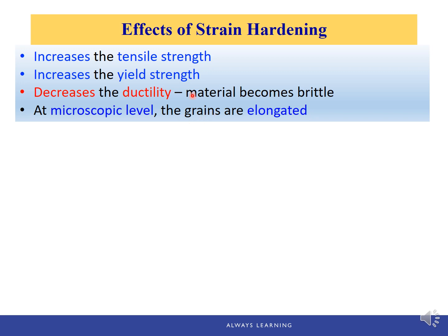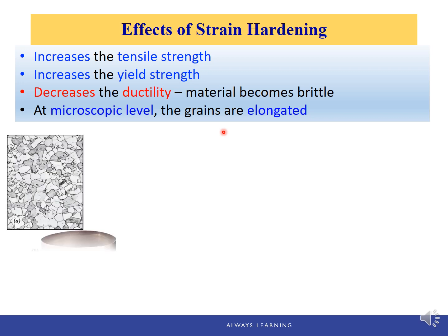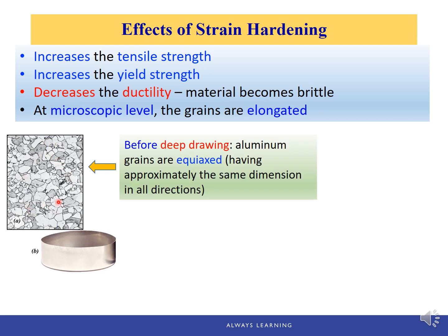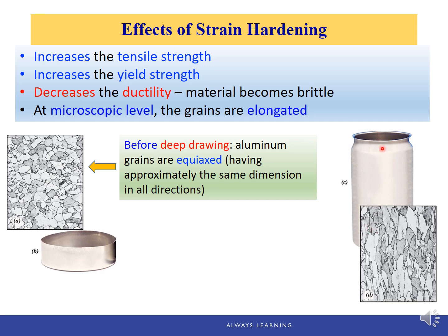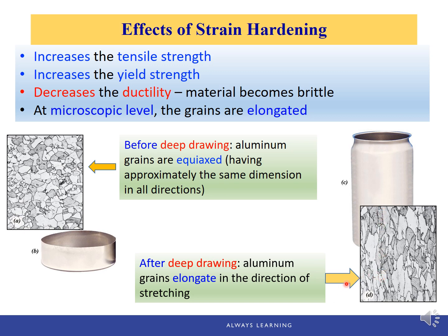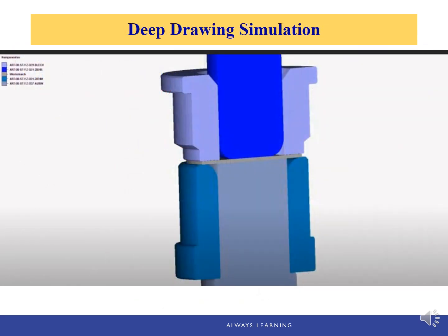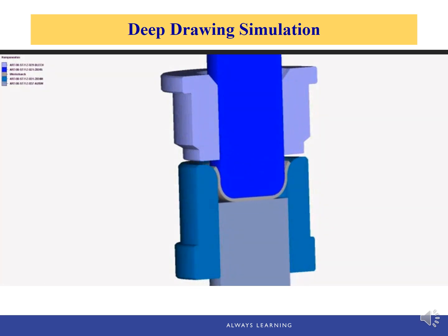So let's take a look at the shape of the grains before and after deep drawing. Before deep drawing, we have a piece of aluminum, and here is the photomicrograph, and from this micrograph we can see that the aluminum grains are equiaxed, which means they have approximately the same dimension in all directions. After deep drawing, we have this aluminum beverage can formed, and now the microstructure shows that the grains are elongated in the direction of stretching. And this is the simulation for deep drawing process.